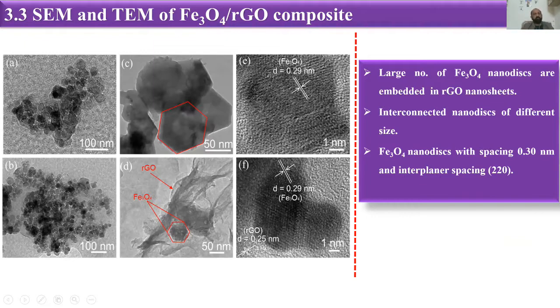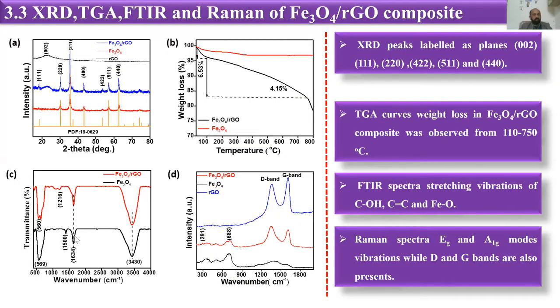And then again, we have done XRD, TGA, FTIR, and Raman spectra of our Fe3O4 RGO nanocomposite, and we have got the indexed peaks for our system. And we have got the desired peaks for our FTIR and Raman spectra, and we have got the D and G bands of RGO, which confirms that the RGO is wrapped by our Fe3O4 system.